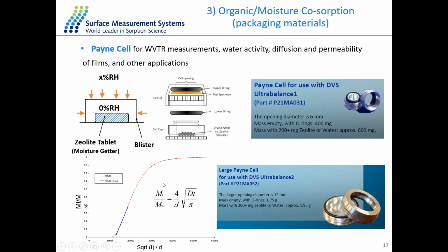And according to Fick's law, we have the thickness of the film sample, we have the mass at equilibrium state, then we can do the plot, and from the slope, we can calculate the diffusion constant of the material, as well as the permeability of the molecules.